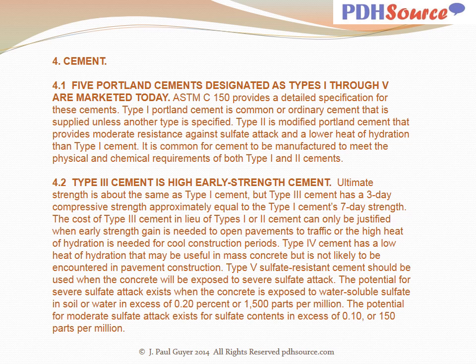Type 5 sulfate resistant cement should be used when the concrete will be exposed to severe sulfate attack. The potential for severe sulfate attack exists when the concrete is exposed to water-soluble sulfate in soil or in water in excess of 0.2% or 1,500 parts per million. The potential for moderate sulfate attack exists for sulfate contents in excess of 0.1% or 150 parts per million.